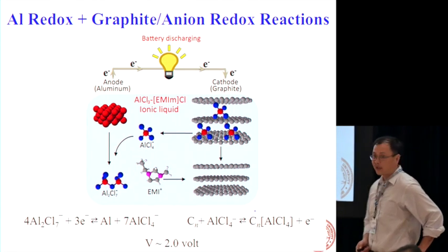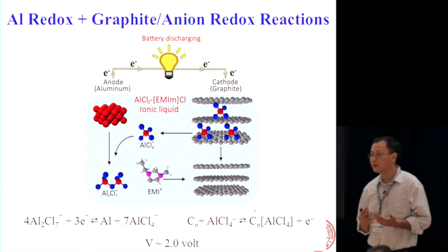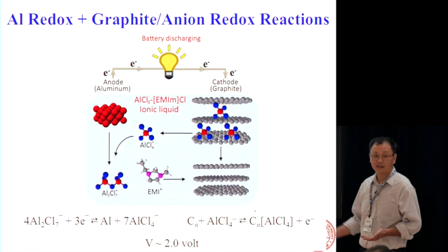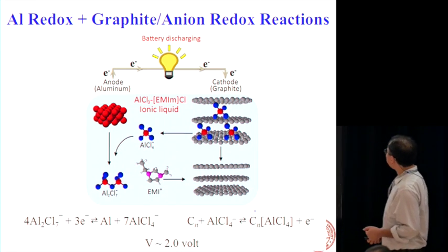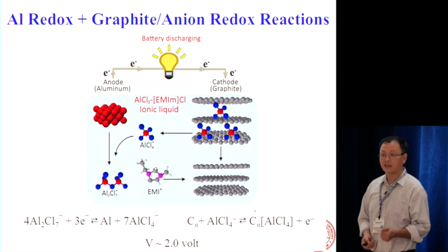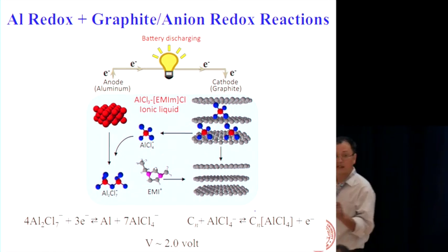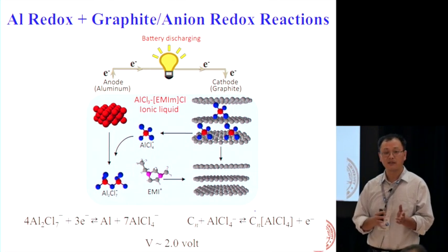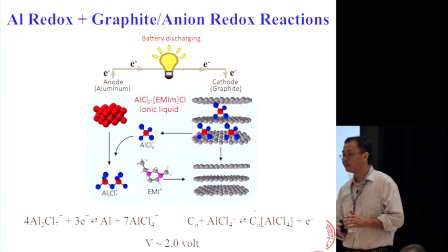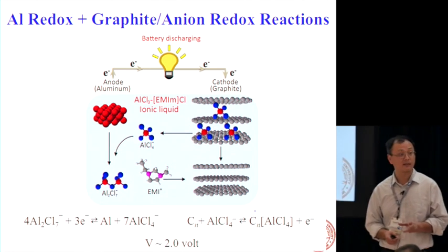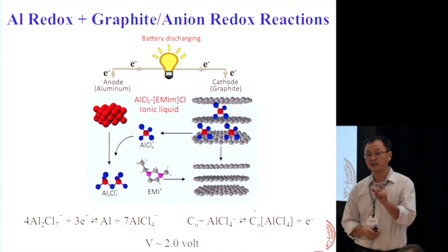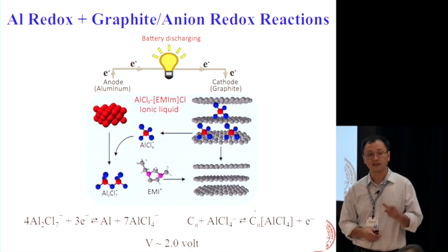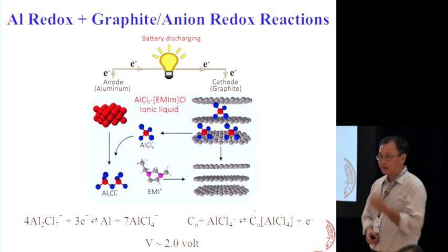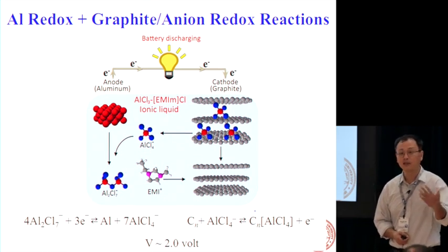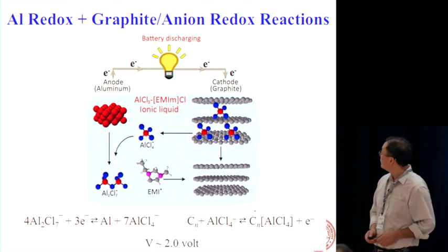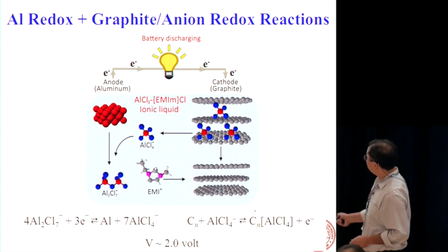And 2 years ago, we actually tried about 150 compounds on this side. Okay, try to combine with aluminum. But at the end, we accidentally found that if you mix graphite into some oxides and try to make a battery, you actually get some battery behavior, and you get some capacity, okay? And then we figured out it's not the oxide that's giving the capacity, it's the graphite. So it's a very accidental result. Okay, we add graphite because we want to have conductivity on this other electrode. So now we know what's going on.